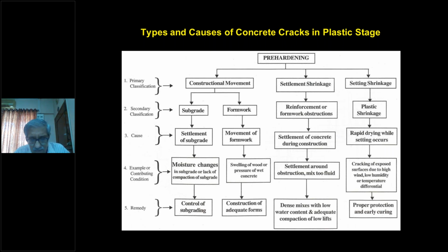Dense mixes with low water content and adequate compaction of the lower lifts, and therefore this can be remedied or completely removed or controlled. The last is the setting shrinkage, which we also call plastic shrinkage. When concrete is very, very young, just born in the formwork, and the structure is a slab or a thin wall, plastic shrinkage cracks occur when the surface is not protected.